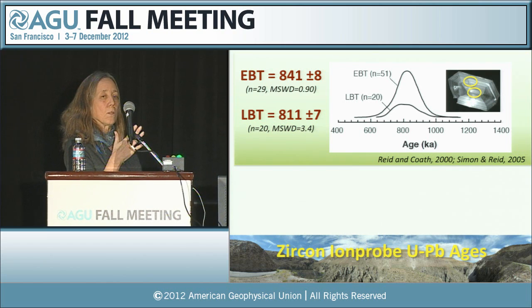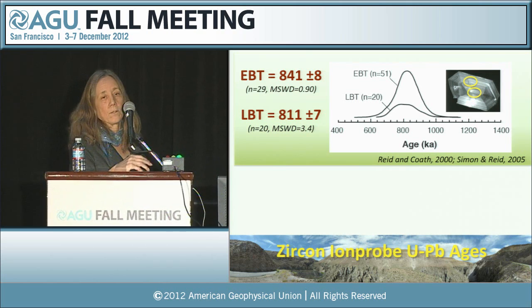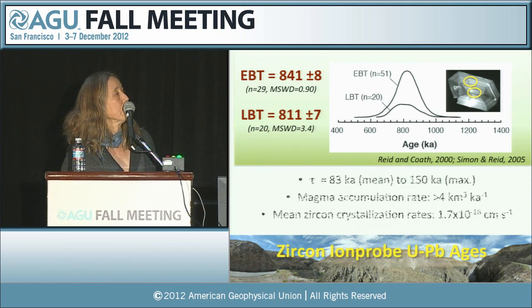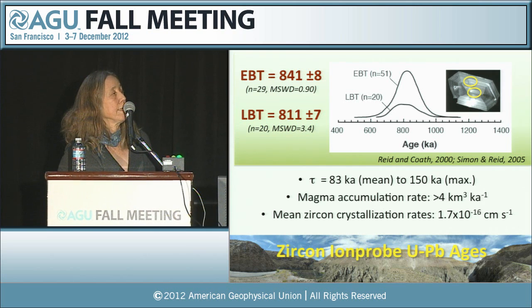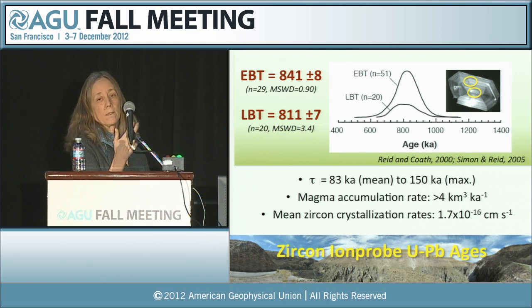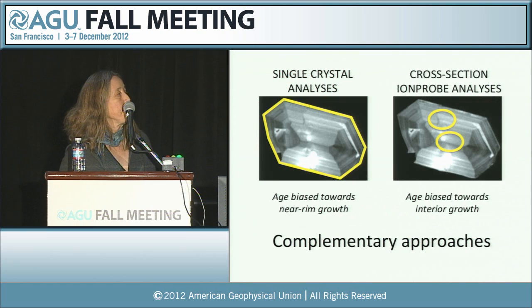But once you remove things that look like they probably crystallized close to eruption, it actually turns out to give a fairly coherent age of about 850,000 years, which now works out to a tau of 83,000 years as an average, so more than an order of magnitude older than what we were saying before from the single crystal results, and magma accumulation rates and zircon crystallization rates that are, of course, more than an order of magnitude lower as well. So clearly, these differences in the ages that we ascribe to the zircons are giving us some very different ideas about rates of magmatic processes. Now, I really want to emphasize the fact that these are really complementary approaches.